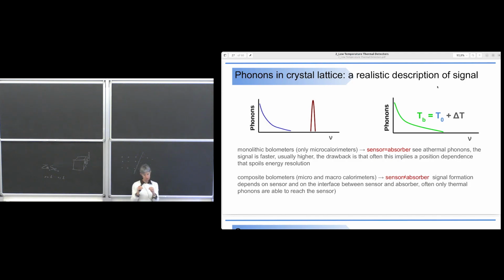In the case of CUORE, we have a thermistor that is glued on the crystal. And what we think, again, at the end, we do not have all the tools that are needed to fully understand the behavior of the detector. But according to our understanding, we read out a signal that is produced by thermal phonons. And this is also because we have two different interfaces. One is the absorber toward the glue, then we have the heat capacity of the glue, and then we have the interface between the glue and the thermistor.